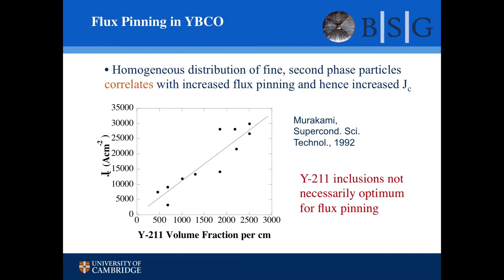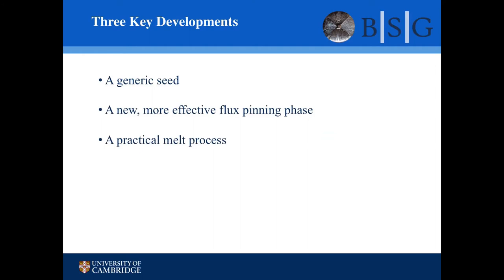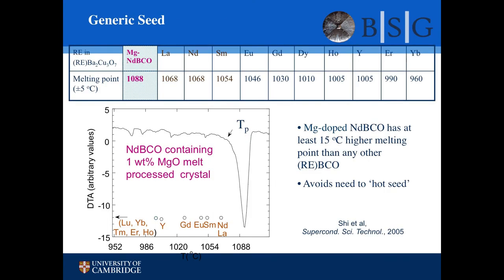We can correlate ability to carry current with the volume fraction of these second phase materials, which indicates that flux pinning is strong. But it may be that these 211 inclusions are not the best way of pinning magnetic flux. So I'm not going to dwell too long on this, but I just briefly want to mention three key materials developments. And the first thing is a generic seed. If you look at the materials that are lanthanum barium copper oxide, neodymium barium copper oxide, samarium barium copper oxide, the light rare earths, they tend to give you the better properties. But their decomposition temperatures are high. So it's okay if we want to grow yttrium barium copper oxide, we can use samarium barium copper oxide to seed it. But what if you want to grow samarium barium copper oxide?